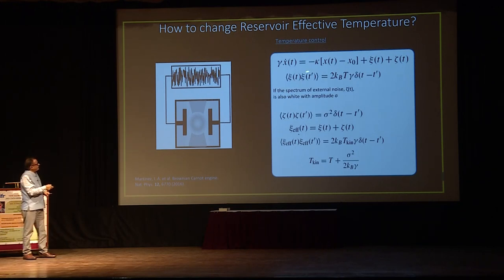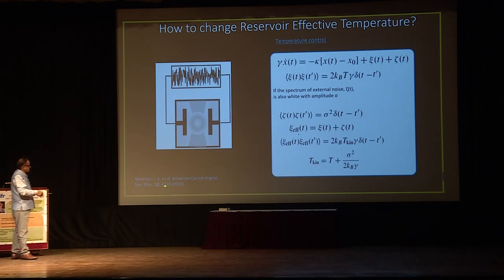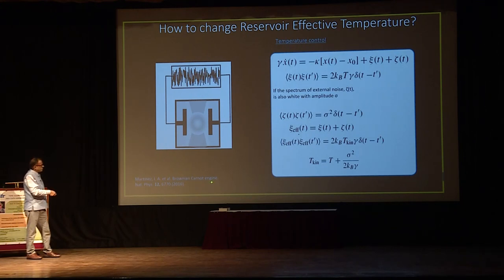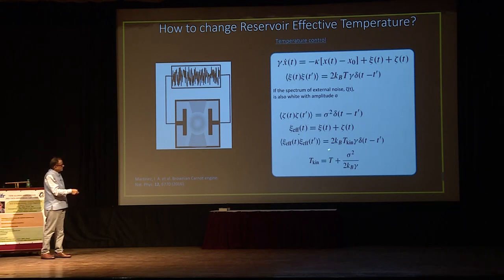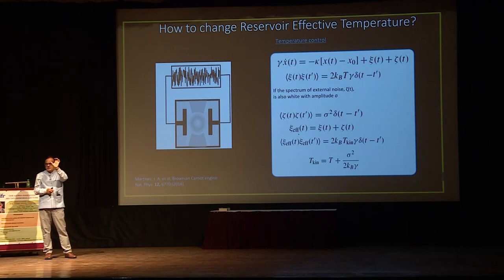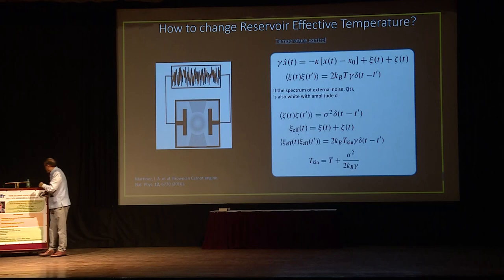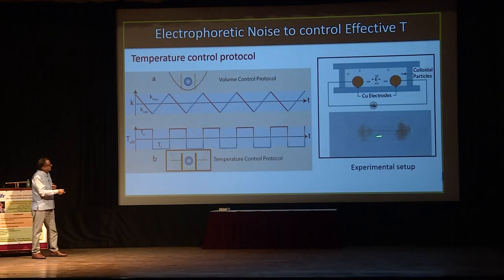And if you solve the Langevin equation, which is done in this 2016 heat engine paper on the Brownian Carnot engine, the T effective gets enhanced, not only the normal temperature of the bath, but also something which depends on the strength of the noise. This is the electrophoretic noise. This is the noise on the capacitor. Now you have a way to control the effective temperature of this. So this is the experiment we do.